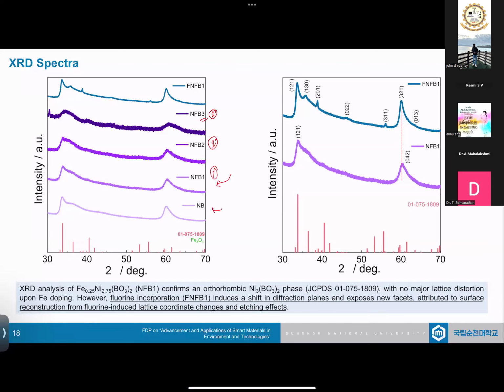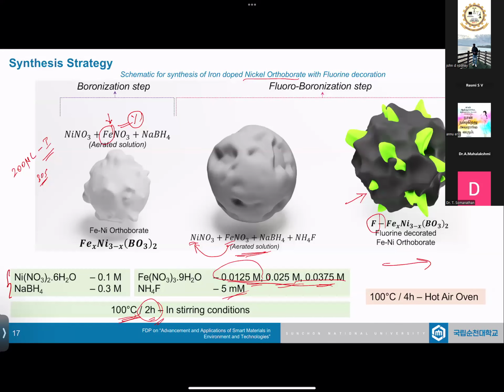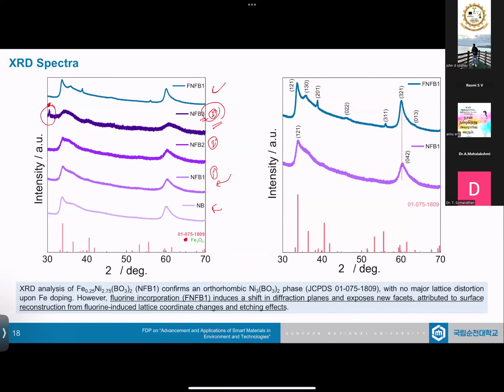This is the core material, this is the NB, nickel orthoborate, and this is the fluorine incorporated one. So when we went with respect to more iron, what happened is we found one peak over here, which is Fe2O3 peak, a separate impurity peak came up, which we don't want. We just wanted to alter the system. We don't want to change the entire phase. So what happened? We stopped in that NFB3. As I said here, we only checked for 3 different doping. And then to the best material, what we did was we did the fluorine etching process simultaneously while we are doing the synthesis.